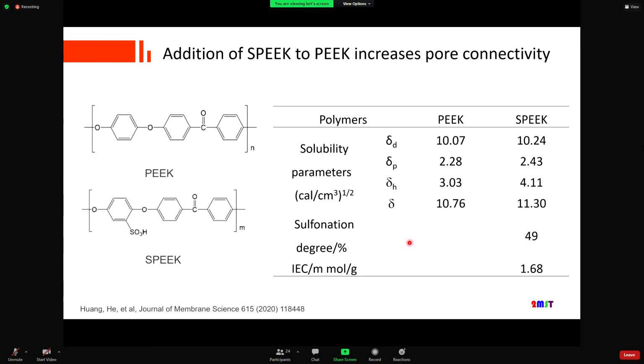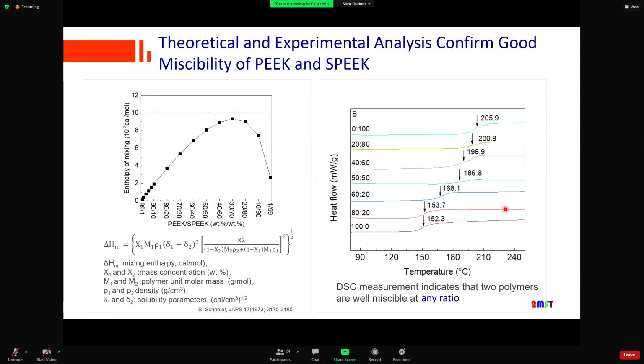If sulfonated PEEK (SPEEK) can give us interconnected pores, why not add a certain amount of SPEEK into the polymer system to control the pore structure? The solubility parameters of the two polymers indicate that they might be very compatible. We use the Flory-Huggins enthalpy of mixing criteria to determine the compatibility of the polymers. It shows that below a threshold, the two polymers are actually rather miscible. And our DSC measurement indicates that the glass transition temperature of the two-polymer mix shows one shift, which indicates that the two polymers are compatible at a molecular scale.